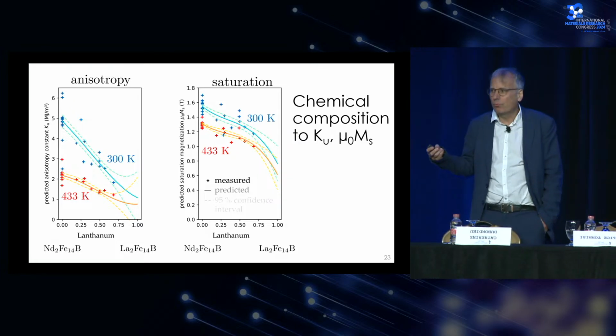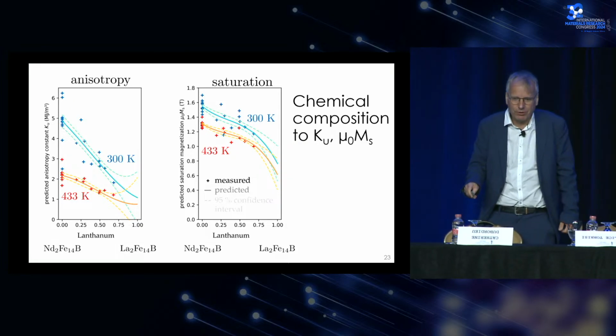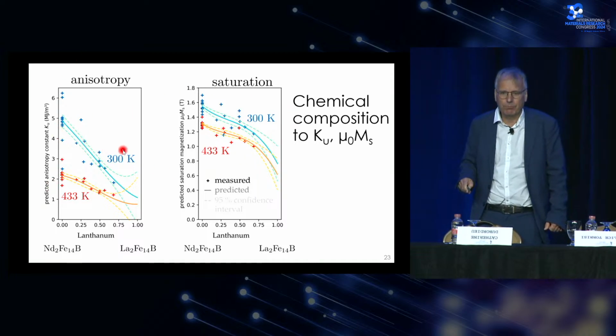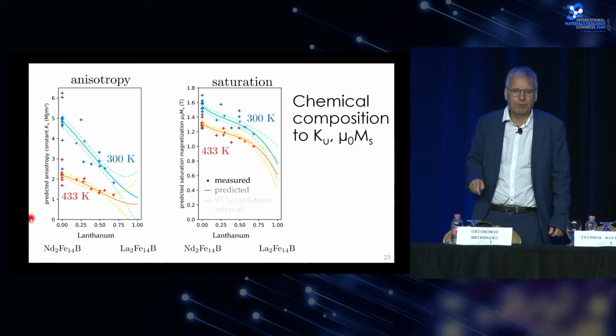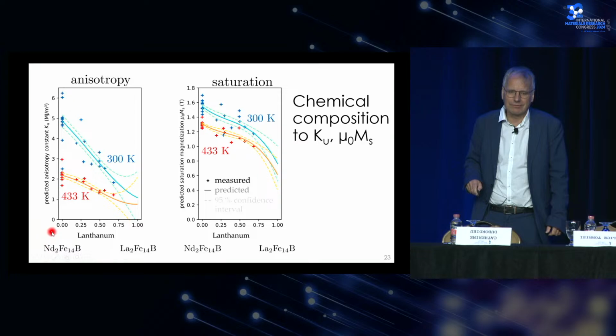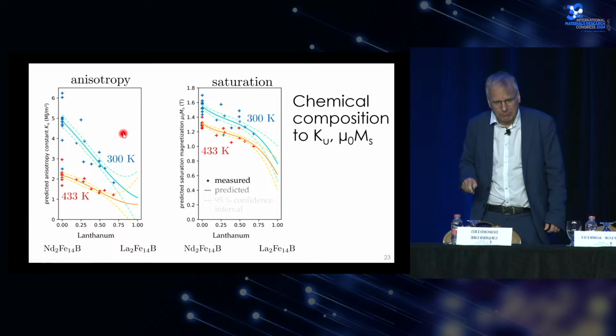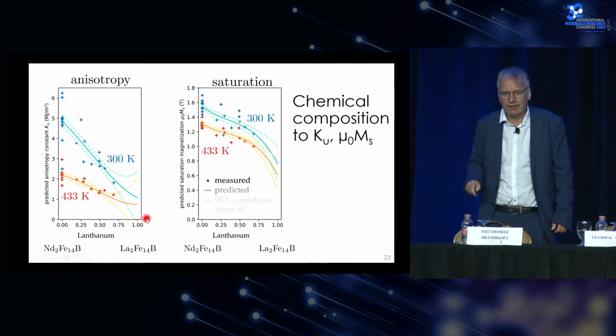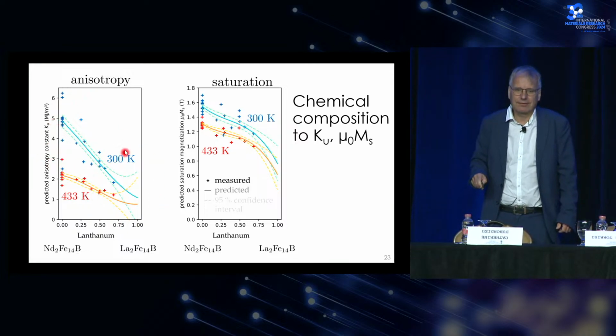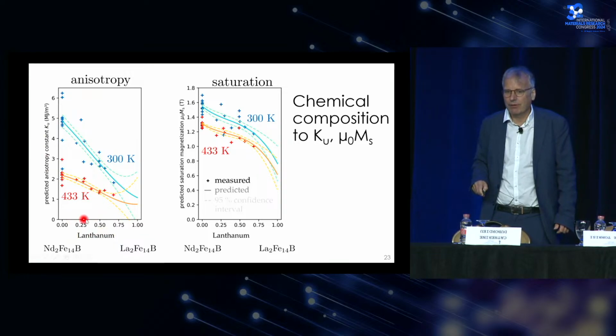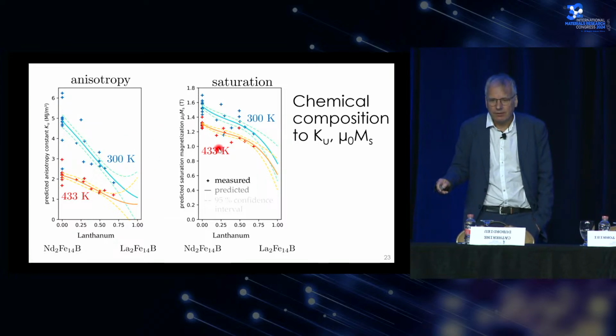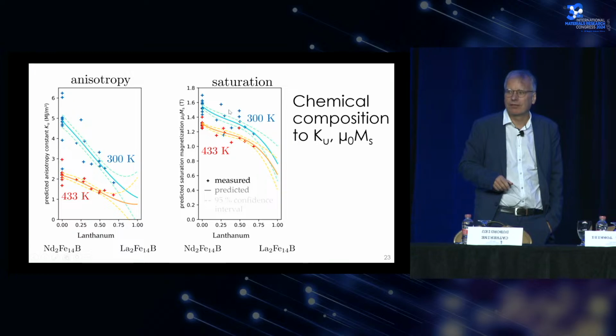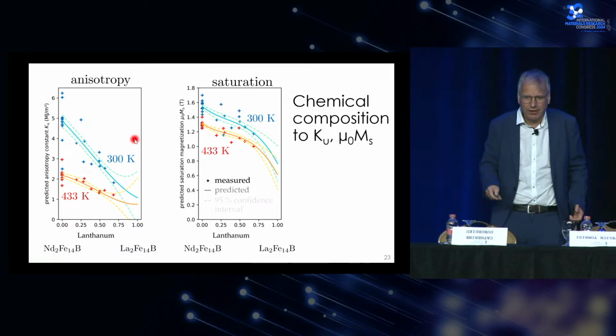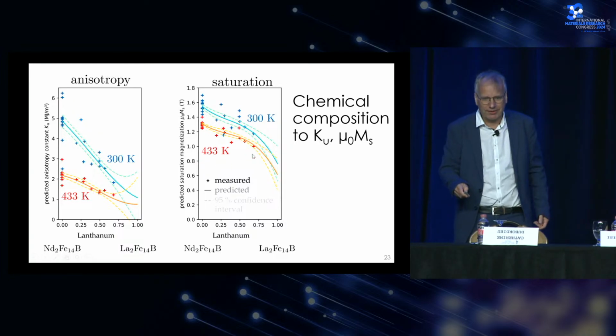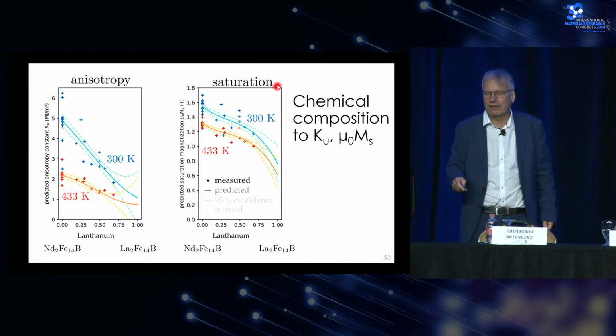Okay, now we already have a tool to play around, so we can go to the computer and say, what will happen with my intrinsic magnetic properties if I change my chemical composition? For example, if I go from neodymium iron boron and then start to replace neodymium with lanthanum, how will the anisotropy constant change at certain temperatures? And this you can see on the left-hand side. So we see how the anisotropy changes if I change the chemical composition. We can do the same with the saturation magnetization. This is useful because engineers can now play around, put in a chemical composition and see what is the expected anisotropy or magnetization.